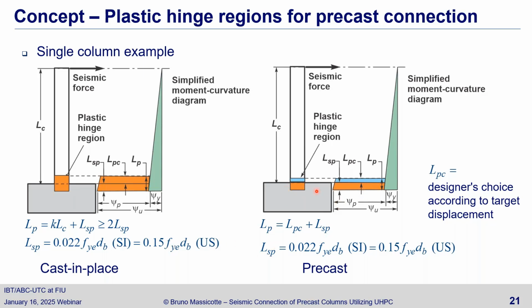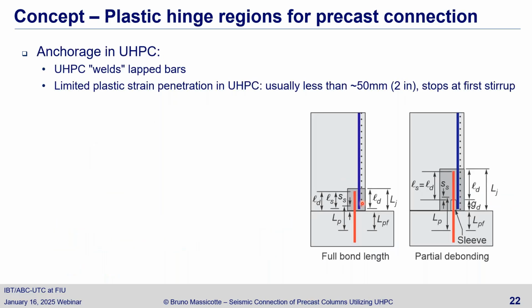And if you need more, depending on the seismic zone you are in and the demand on displacement that you need, then you may have to extend the plastic hinge within the UHPC. However, as I said before, that cannot be done because in UHPC there's no plastic strain penetration. So we have two solutions. If your plastic deformation occurs only in the footing, this is a configuration you may have.